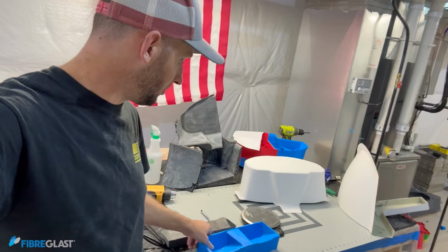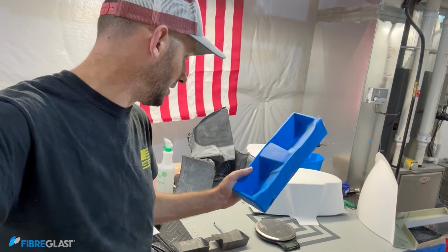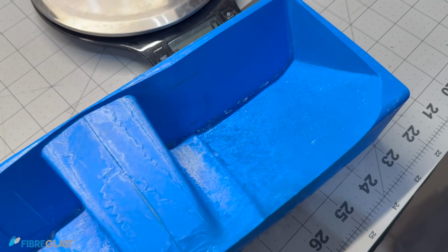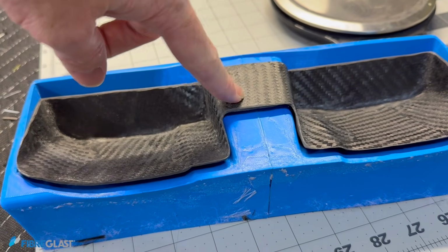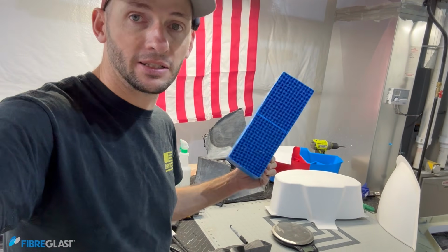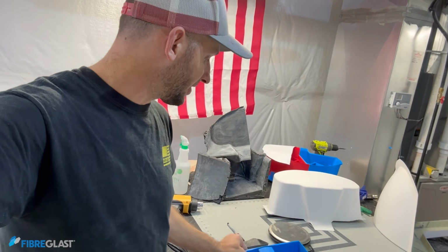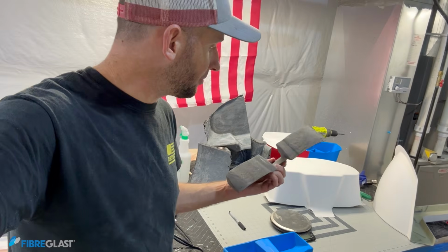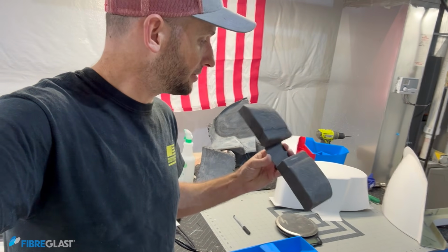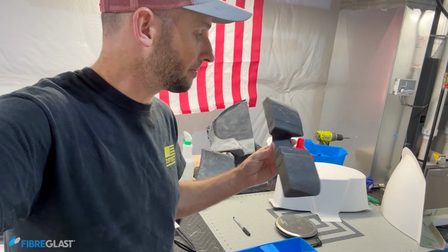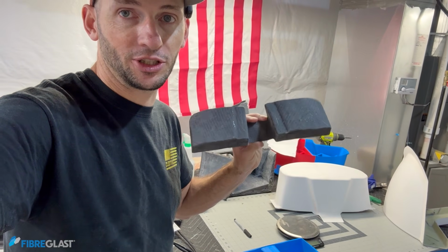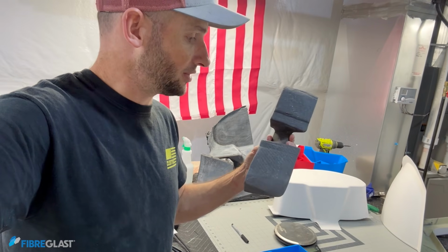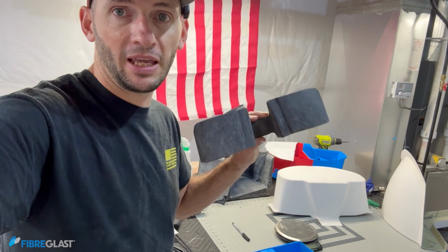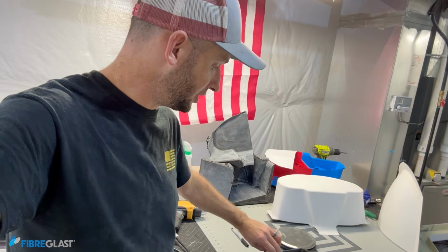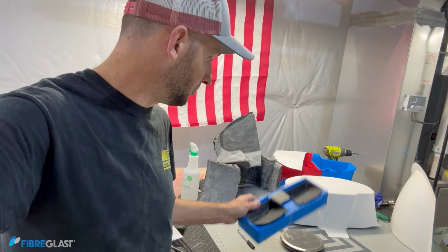The do's and don'ts. One, I screwed up, and I was basically just impatient. I put the part under a space heater to get it hot, and in doing so, I warped the mold pretty bad. So this mold is now scrap. The peel ply idea worked out perfect. And if I didn't mention it before, the reason I really wanted to do that is because I'm going to be bonding this into the helicopter, and I wanted that peel ply texture to help me with that bonding surface. And so it kind of killed two birds with one stone. It gave me that texture, but also worked as a perfect release agent to get the part out of the mold. So that was really cool.